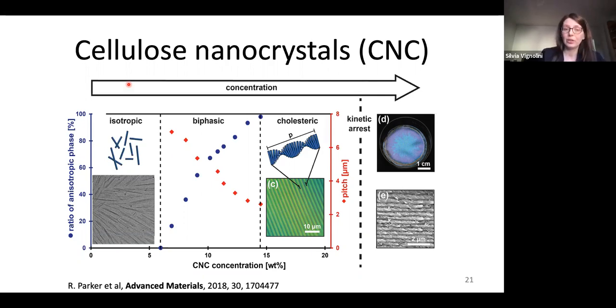So if you extract the cellulose nanocrystal from any plant's resources, from cotton, from wood pulp, all the results that I'm showing you essentially are obtained mainly from cotton, that we take from the cotton linters. You can even use the part of the cotton that is a leftover from the paper manufacturing company or from yarns, because they are too short to be exploited to make proper and resistive fibers. So we take this small leftover from this industry, and then you can do acid hydrolysis, and this acid hydrolysis mechanism releases what we call cellulose nanocrystal particles, that if you look at them under the TEM microscope, they look like this. I don't have a scale bar, sorry, but they are about a few hundred nanometers in length and only 3 nanometers in thickness.